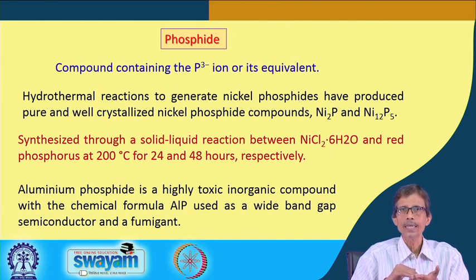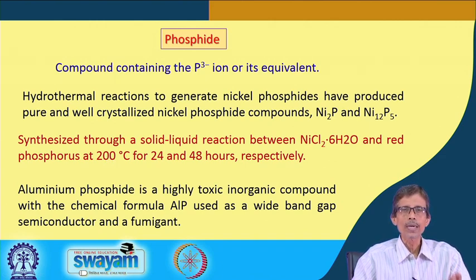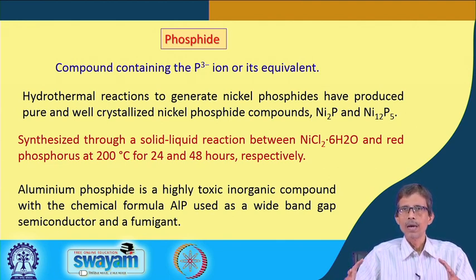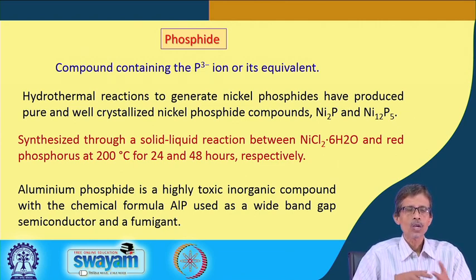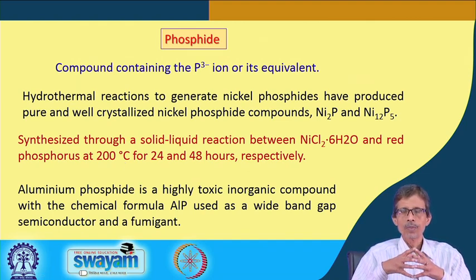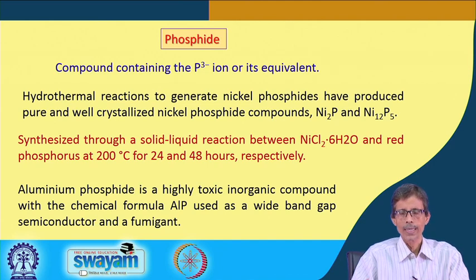The temperature we are considering is only 200°C. We rise slowly from room temperature — say 25 to 28°C — up to 200°C in a stepwise manner. That regulated temperature is well monitored; nowadays all these hydrothermal reaction chambers are available in college or university laboratories. We give the example of reaching 200°C over a time frame of 24 to 48 hours, monitoring the rate of temperature increase throughout.